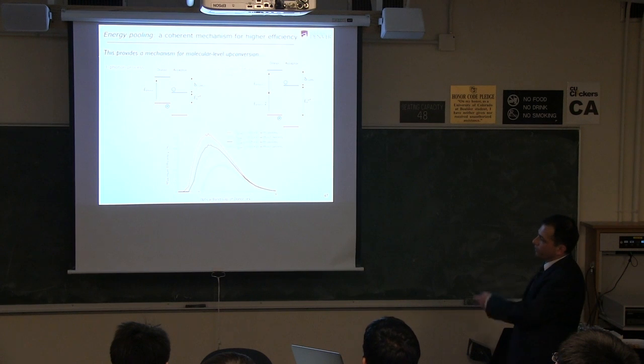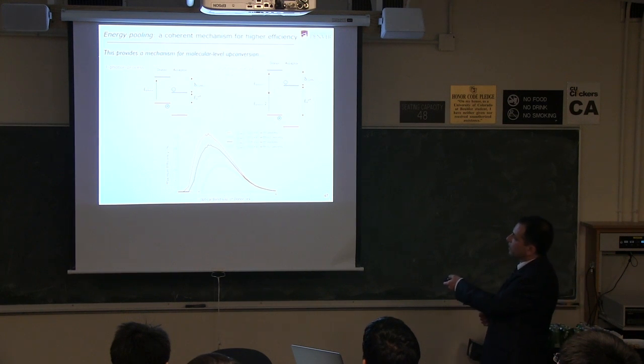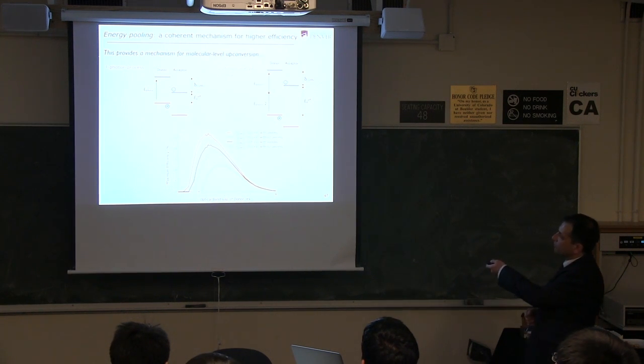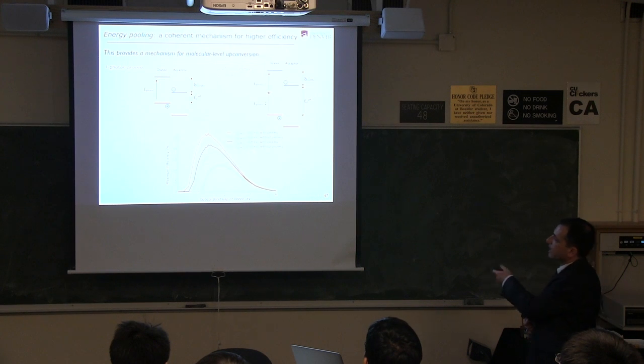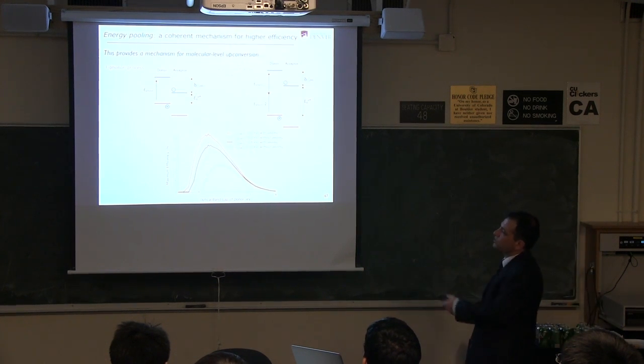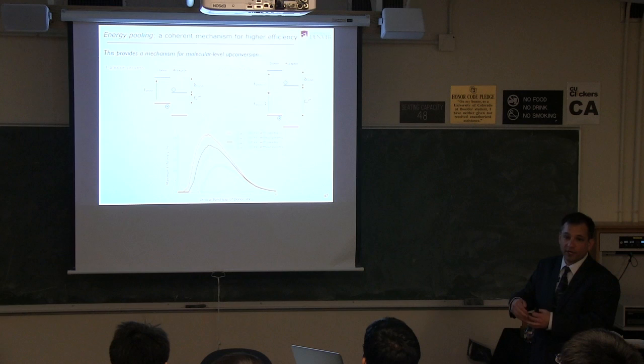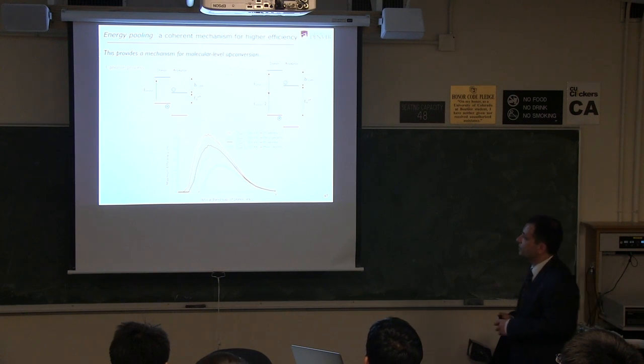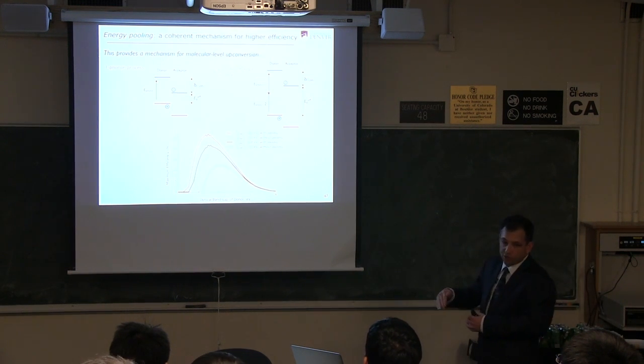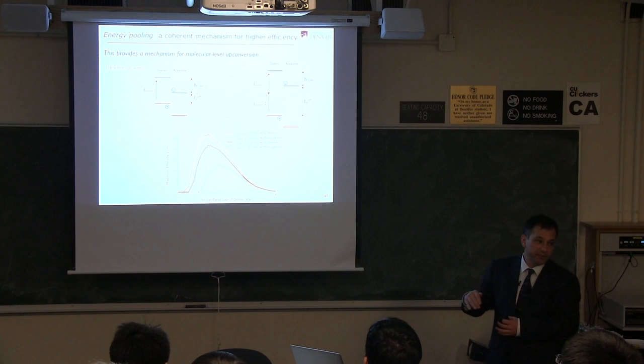And if you just run through the same kind of calculations I showed you before, if you start with a system that has a delta LUMO of like 0.5, with or without pooling, you see enhancement in the efficiency. If delta LUMO is larger, 0.8, you can nearly double the efficiency by incorporating the pooling mechanism. This is all still below the Shockley-Queisser limit, 31% limit.